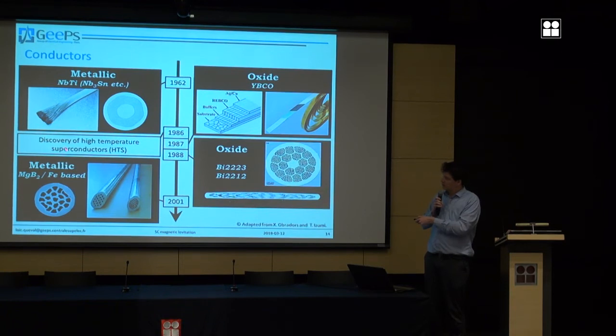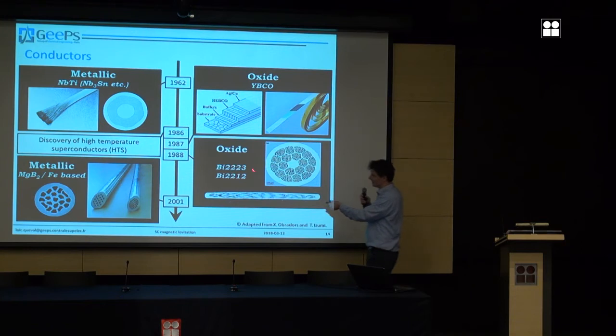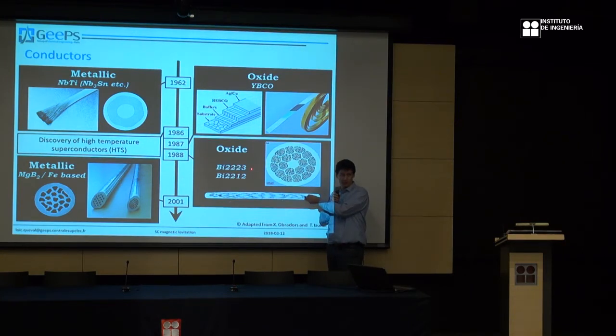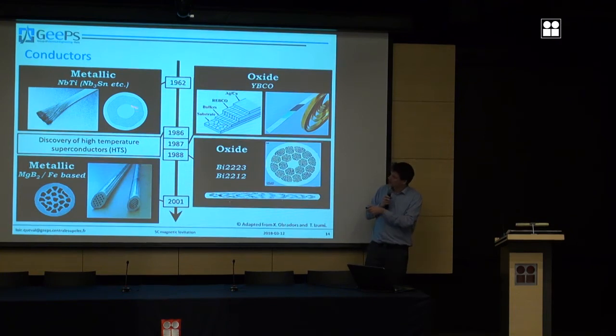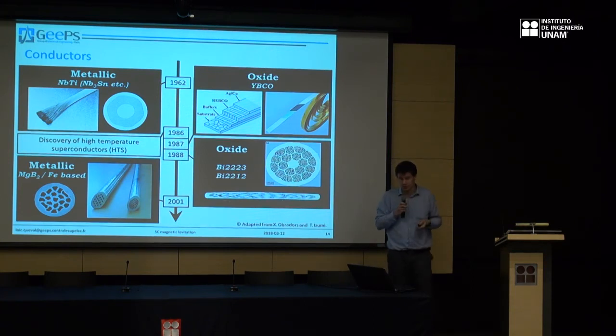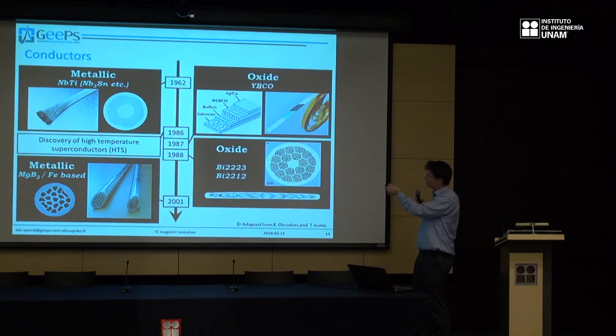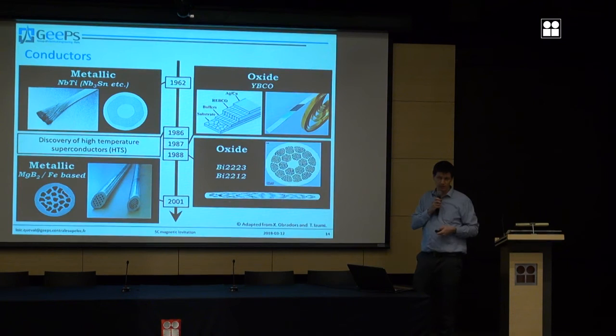Then in 1986, we discovered what we call high temperature superconductors. It means the TC is higher, more than 35 Kelvin. And right after, these two could be manufactured as tapes, okay? Actually, this one here was manufactured as a tape first, in 1988. So that's why we call it 1G, first generation, and we call it BSCCO. Then a little bit later, this other one was manufactured. It was discovered a little bit before, but manufactured as tape a little bit after. So we call it second generation, and we call it YBCO. And you can buy it right now.